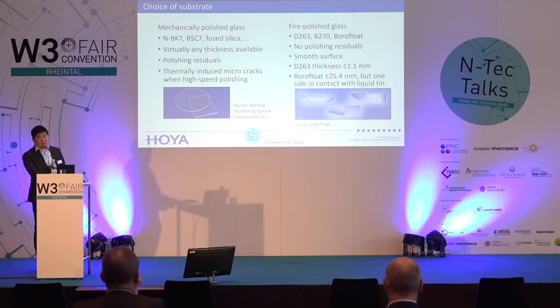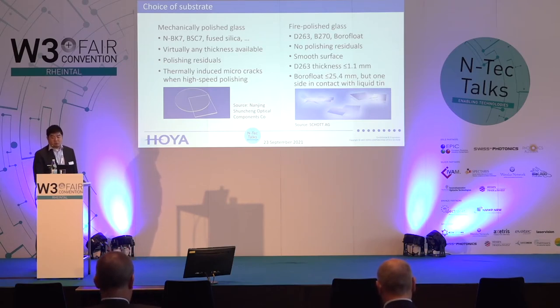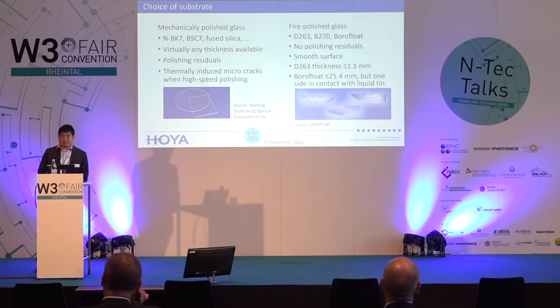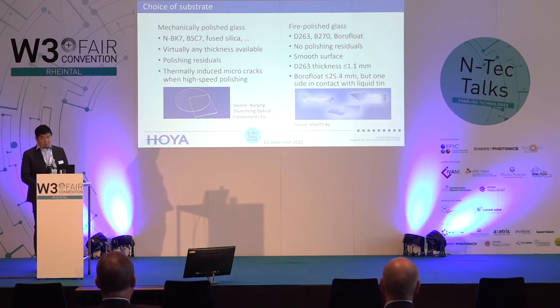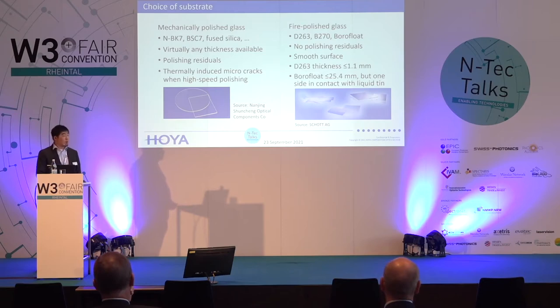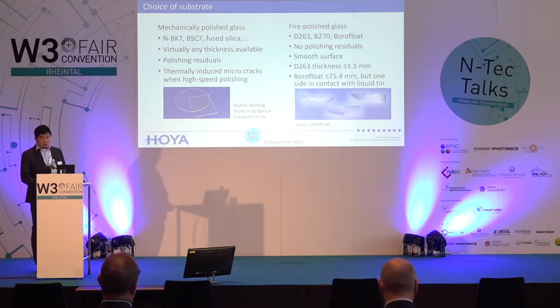So in recent years, filter companies looked at fire-polished glass or float glass like D263, B270, or borofloat. There are no polishing residues necessary, or they do not occur. One drawback is that, for example, D263 is only available in 1.1 millimeter thickness as a maximum. And as I explained, with these modern coatings, the thicker they become, the more stressed they are.